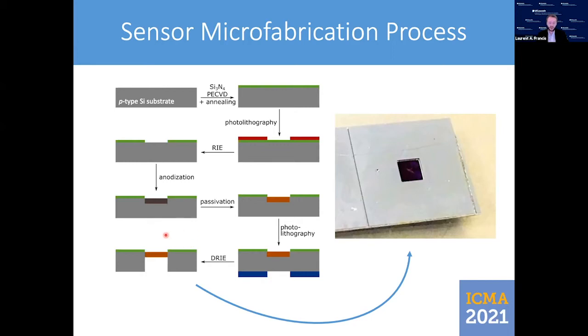This will automatically stop on the passivated porous silicon. Once we reach this porous layer from the back, the pores are fully open and we have thus a silicon membrane as illustrated here in the picture, seen from the back.